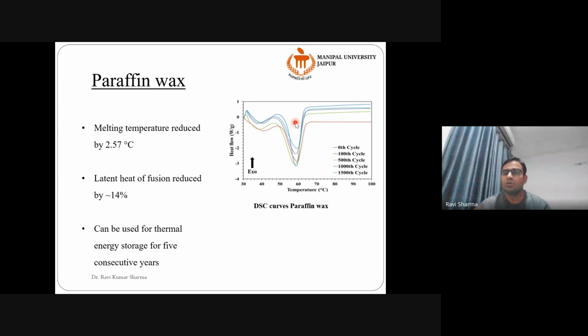So I have overlaid these curves between 0 to 1500 cycles. This zeroth cycle means the fresh material that we had received from the vendor. Then after 100 cycles, after 500 cycles, after 1000 cycles, and after 1500 cycles.